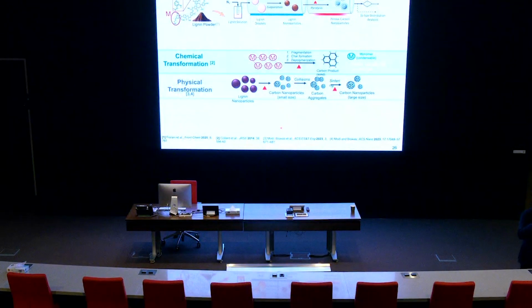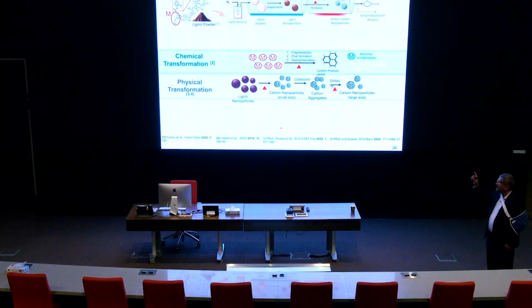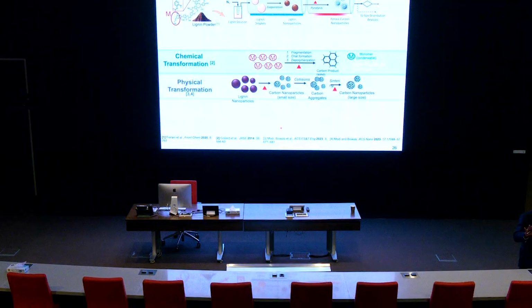So this is a very good point. I just picked a certain lignin. Lignin is of many different kinds, right? The polymeric structure with the unit, like I call it M here, could vary, right? And certain lignins are not even water soluble, as I just mentioned in passing. In that case, yes, there is some pre-processing to be done. Like you want to maybe get it in a smaller size so that you could spray it and run some of these reactors. So this was a very controlled study, intentionally a certain, I can't remember the exact polymeric form of it, which is in some sense clean and also water soluble, right? But you can also take other forms of lignin and make them water soluble, as you're saying. If I do that, if I go all the way down, I'll have to consider that in some form as a penalty in my calculations, right?